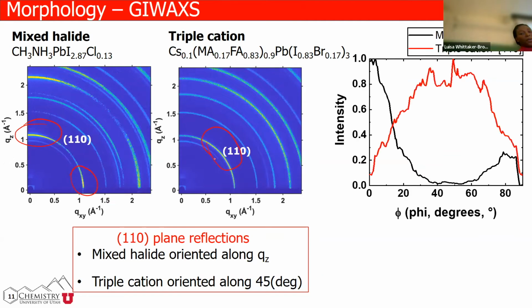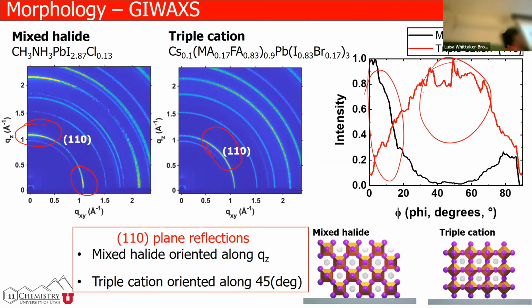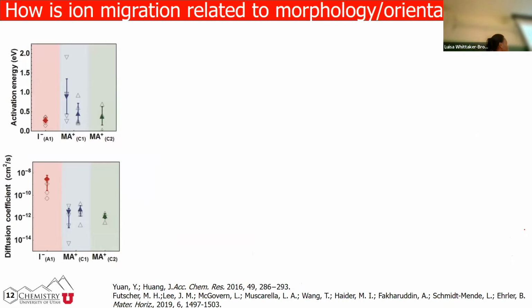All right, so the thing is that then, again, we can azimuthally integrate this, so we get most of the intensity here for the mixed halide, triple cation over here. So in terms of orientation of the film with respect to the substrate, and this is important in the next slide, right? We know that for the mixed halide, the 110 is oriented in this direction. And then for the triple cation it is oriented in this direction. Okay? All right, so why is that important?